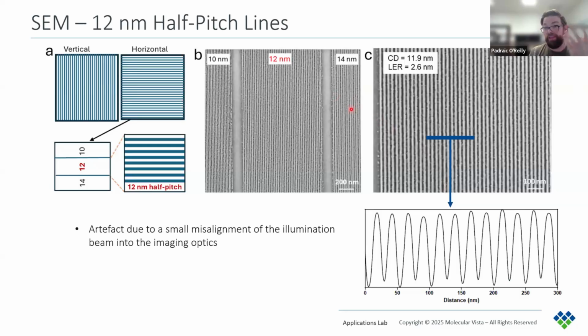So here we have some SEM images that they took on the developed sample, gradually zooming into this 12 nanometer half pitch lines. You can see from this zoomed in image, and especially from this line profile here, again, that every second dip is shallower than the previous.